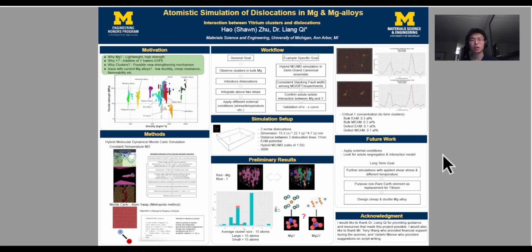And from this simulation snapshot, I was able to propose a possible phase match according to the phase diagrams. I divided all the clusters into 2 categories, large ones and small ones. Large ones have over 15 atoms, while small ones have less than 15 atoms.